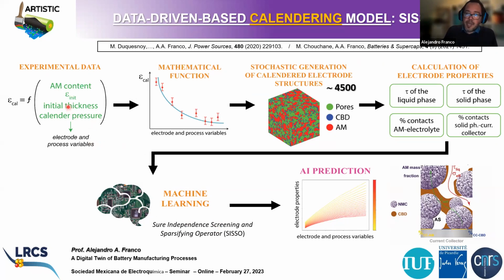We have first built a data set where you have as an output the porosity of the electrode after calendering, and as an input you have the formulation of the electrode, which is actually the active material content in weight percentage, the porosity of the electrode before calendering, the thickness of the electrode before calendering, and the calendering pressure. These are the four input variables, while the output variable is the porosity of the electrode. Thanks to this data set, we have derived a correlation function, okay? This is a kind of fitting, right? Relating the porosity of the electrode as a function of these four input variables.